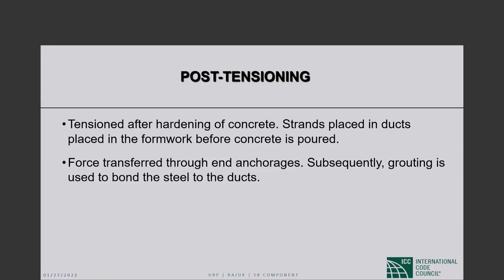So once we apply the concrete, it hardens, then what we do is we feed the strands through the duct. So it goes all the way from one end to the other end. And then we anchor it on one side, and then we apply the pre-stressing from the other side. And then there are grouting ports into the ducts, and we typically inject grout from one side of the duct. The grout comes out on the other side, so we know that the conduits are fully grouted. So it gives you the bonding that we desire.